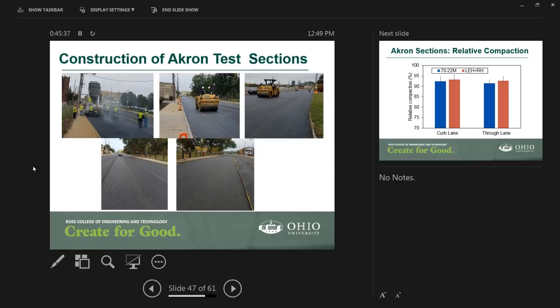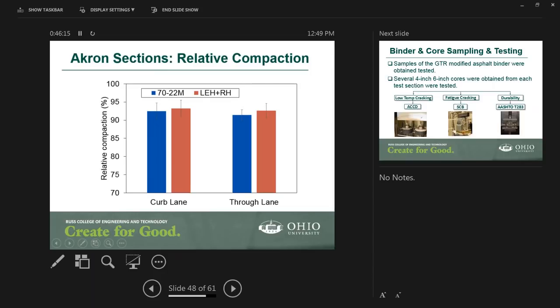One thing that I would like to mention here is that it was October in Akron, around the 60s to 70s, so there was no problem with constructing GTR sections at that temperature, which is a good thing, because before that the contractors were afraid or hesitant to do anything after September with the GTR. But with mid-October, we did not really have any issue.